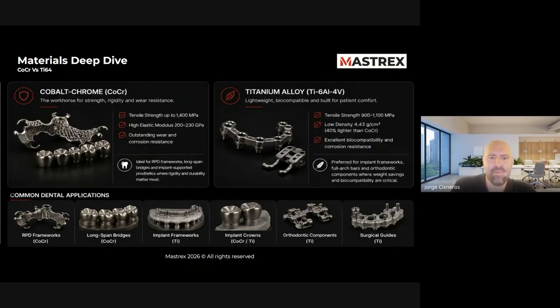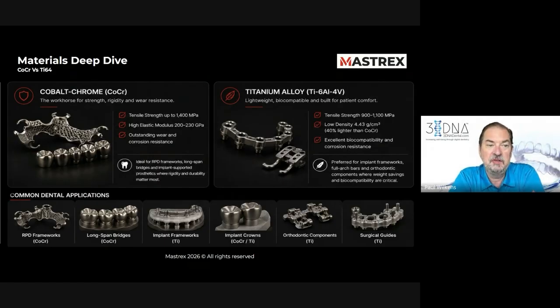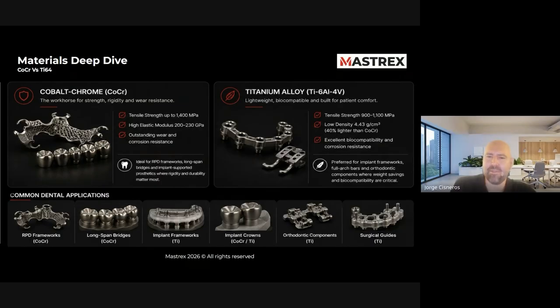Any special considerations if you're welding to either type of these materials, either laser or traditional? I would say there's not too much of a worry as far as welding goes, especially because the 3D metal printing process is essentially a micro weld process. So we often say as long as the material is weldable, it's printable. So these are both very easily weldable materials. Okay. So printing frameworks using a laser welder should be easy. It's very much part of the workflow.